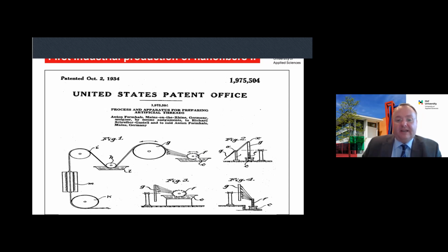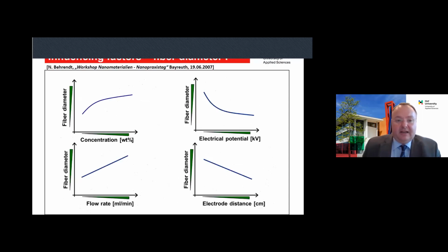Okay. Therefore, it was invented by Anton Formhals in earlier times, and now we have to clarify a little bit what the effects are. In most cases, the aim is to create really, really thin nanofibers, 50 nanometers or maybe less than 50 nanometers. And you can see the influence of the different parameters. At first, of course, if you have a high concentration of polymer in a polymer spinning solution, of course, you have an increase of the fiber diameter.